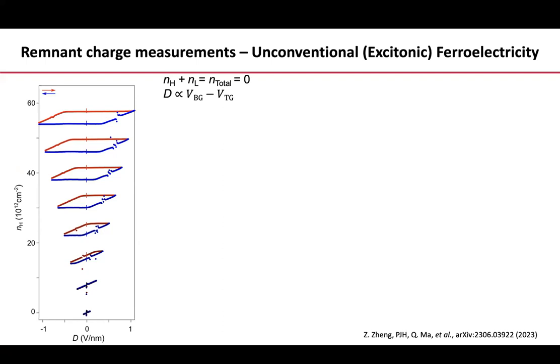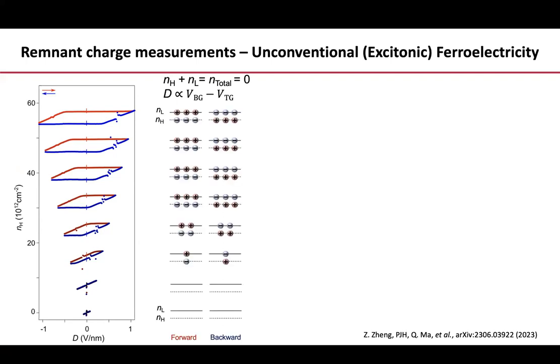I have ferroelectricity where the electric dipole moment of the system can be continuously tuned because the basic unit that is contributing to the ferroelectricity is a continuous, well, continuous integer distribution of excitons in the system that I can vary at will. Rather than having, as in a regular ferroelectric, the entire structure which does and the whole electric dipole changes, here I can add 1, 2, 3, 4 excitons and then the dipole moment increases, increases, increases, okay? So these states have different number of excitons in the system responsible for the ferroelectricity. So an electronic ferroelectricity, not a structural ferroelectricity.